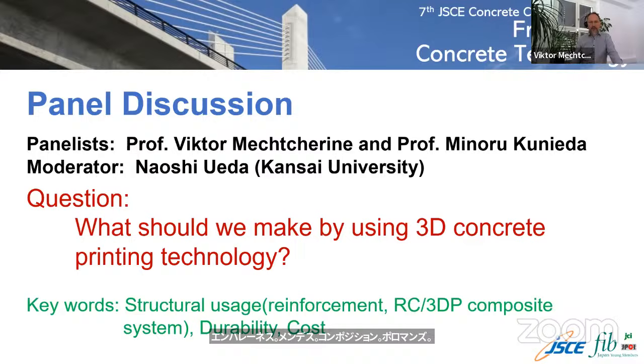Also, the example shown by Professor Kunieda, where we have some supports for the bridge, was also done with this technology, strain hardened cement-based composite. So it's pretty powerful. Short fiber, no problem at all. Of course, we need to adjust the printing a little bit so that the fiber doesn't stick in the print head. It's about a good flow of the material, but it's not a problem as such.